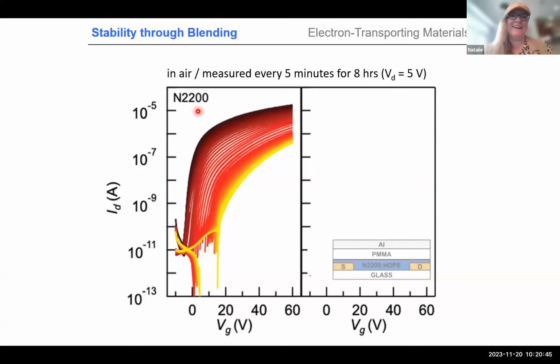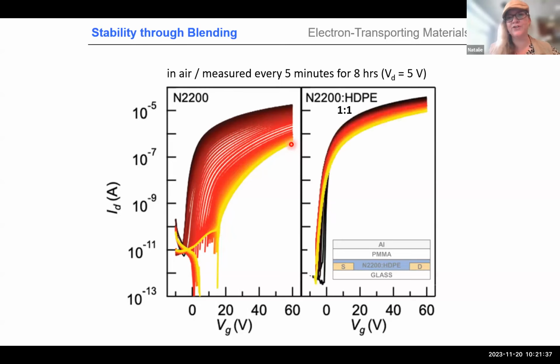More, and that's now a material that all of you should be familiar with. We have that one in specs, N2200. N2200 in transistors leads to N-type transistors, meaning transistors that move electrons around. And electron materials are often a bit unstable when you actually expose them to air. And you see how you gradually and rapidly decrease the transistor performance when you just have N2200 transistors, expose them to air, and after here 8 hours, you see you have exactly the characteristics I showed, with this characteristic bump indicating doping and a relatively low on-off ratio.